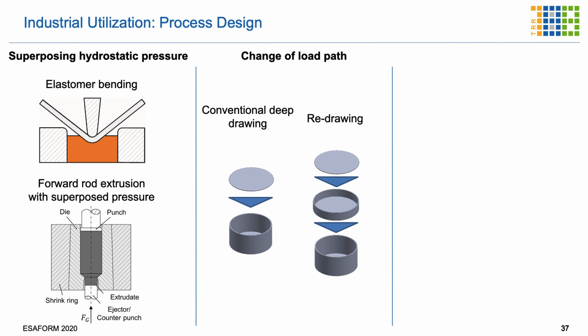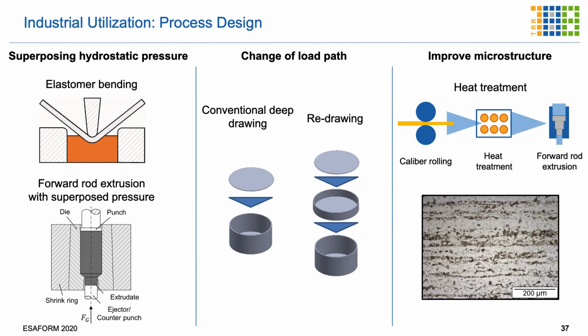We have shown that you can change the process design. For instance, in deep drawing, instead of conventional deep drawing, you can do redrawing and end up with a different damage distribution and hence different performance. What I haven't shown you as well is you can improve the microstructure during the heat treatment and during the rolling, such that the microstructure is convenient to reduce the damage evolution in the process.